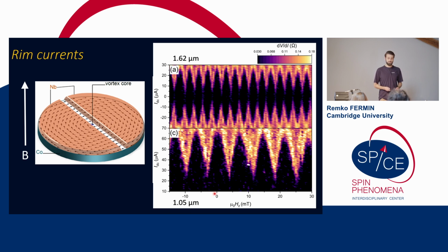Basically this means that in the darker regions we have superconductivity, in the non-dark regions we have the normal metal regime, and the line between them is the critical current. We see that this pattern is characterized by equal width lobes and hardly any decay of oscillation amplitude.